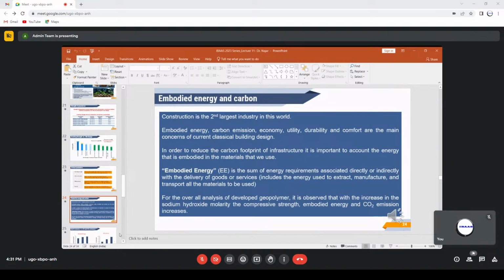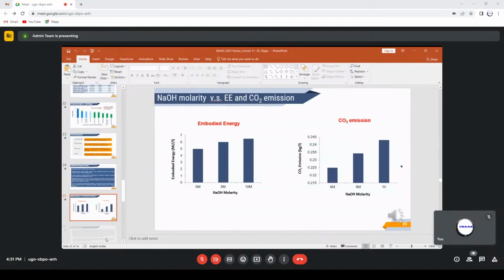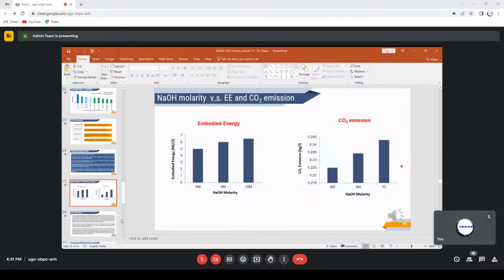For the overall analysis of the developed geopolymer, it is observed that with the increase in sodium hydroxide molarity, the compressive strength, embodied energy, and carbon dioxide emission increase. A comparative study on the variation of embodied energy and carbon dioxide emission with respect to the increasing concentration of sodium hydroxide in alkali activated medium is shown here. The dry mix design used was a mixture of fly ash and laterite in a 1:1 weight-weight ratio.